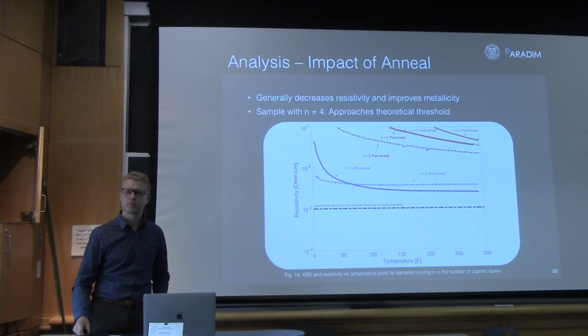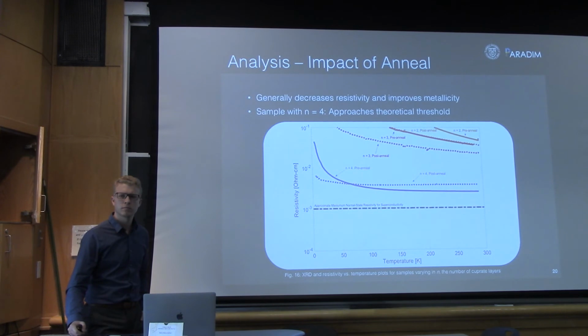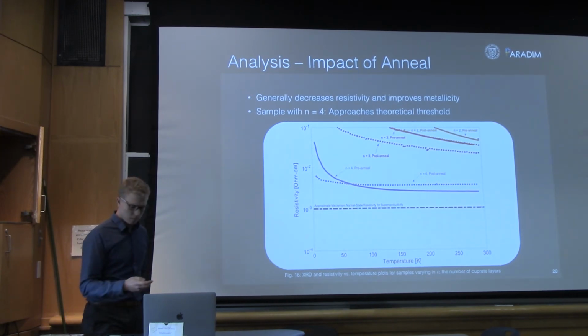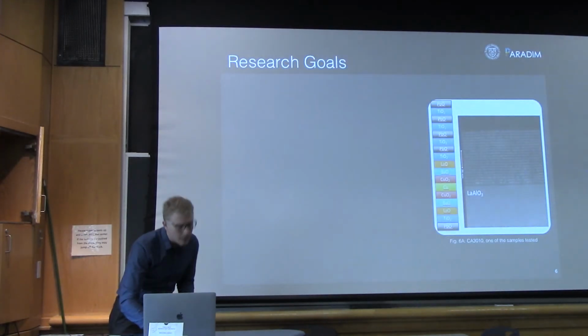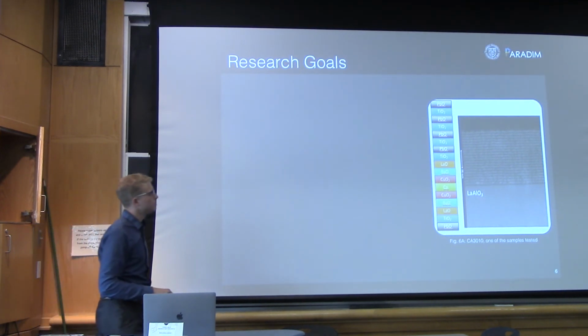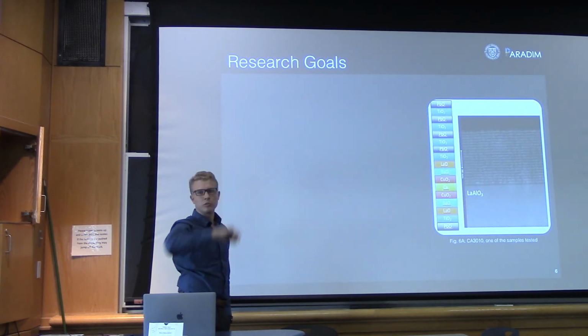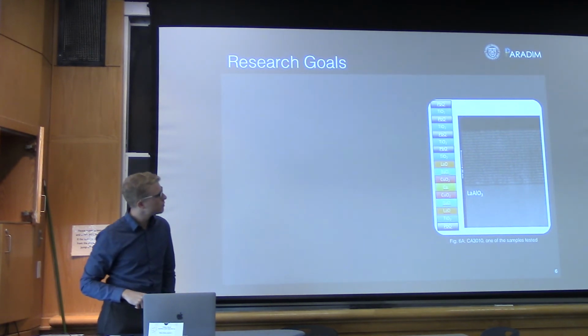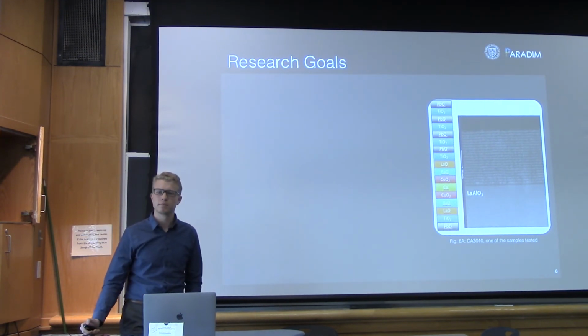So these have got to be reasonably conductive films. I mean, 10⁻³ is not many semiconductors, unless they have enormous dopings, would have that kind of. Maybe I want to go back to probably slide 6, where you have all the elements. Okay, I got the MBE structure. So this is the repeat sequence that you grew for multiple cells? Yeah, so you can imagine that each layer right here is basically its own cell structure. So 20 to 30 times you repeat it over and over again. So this stack of what looks like 20 different oxide films, you then repeat on top of itself 20 times. Yeah, exactly. To grow the film.